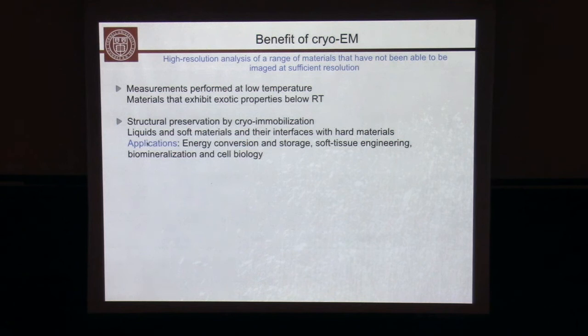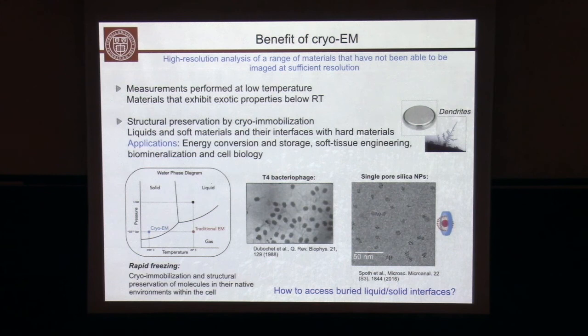So here we want to use cryo-electron microscopy to stabilize a liquid-solid interface and understand how reactions occur and limit performance of lithium batteries. So this is a phase diagram of water, temperature, pressure, and this is where we want to be in order to image liquids or hydrated samples. Traditionally, if you load a liquid or a hydrated sample in a traditional microscope, you have a phase transition into the gas phase, and your biological structure dehydrates and collapses. Okay? So instead, what we do, and lots of biologists have done for many years, we cool rapidly, we load it into the cryo-electron microscope at liquid nitrogen temperature, and we can now stabilize that liquid phase.